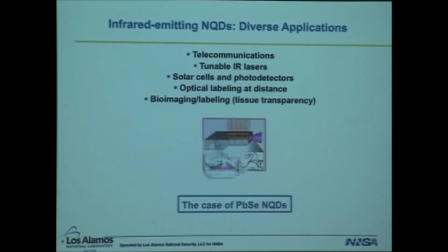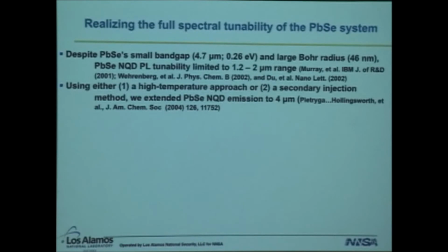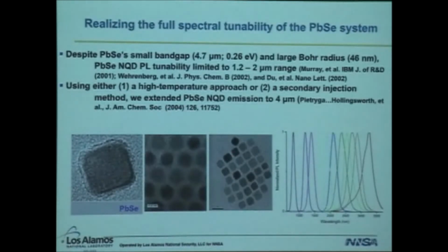And so the case here is that of lead selenide quantum dots. When we entered this arena, there were nice preps out there for high efficiency, high quantum yield lead selenide quantum dots that emitted in the 1.2 to 2 micron range. We were able to develop new methodologies to grow larger and better particles that extended our ability to emit all the way out close to 4 microns. So really taking advantage of the entire range of the bulk band gap of lead selenide, actually.